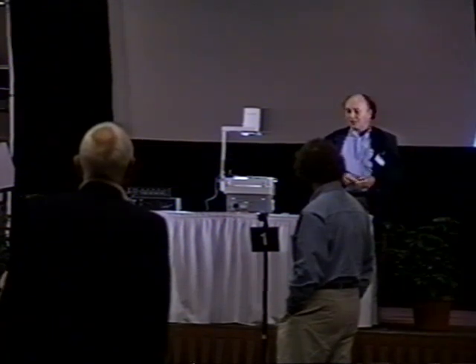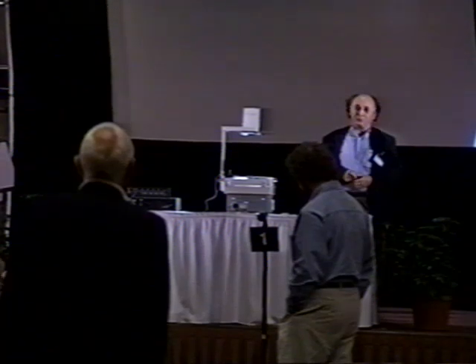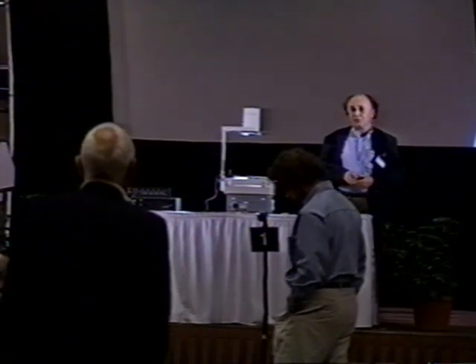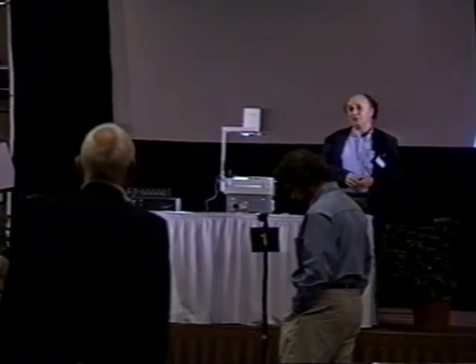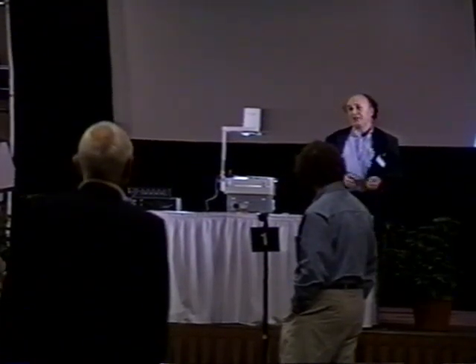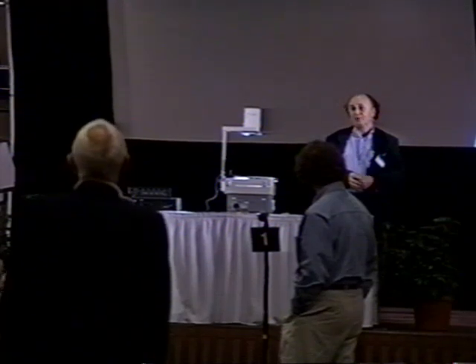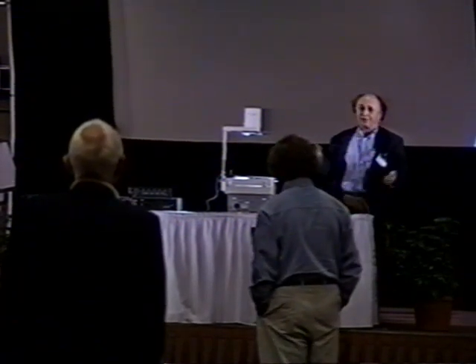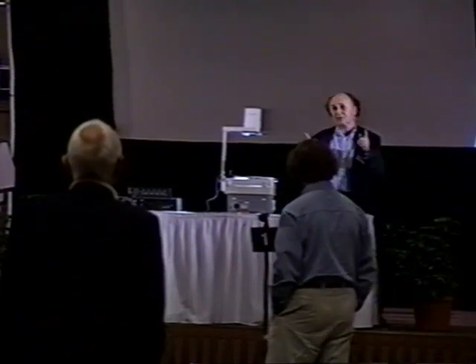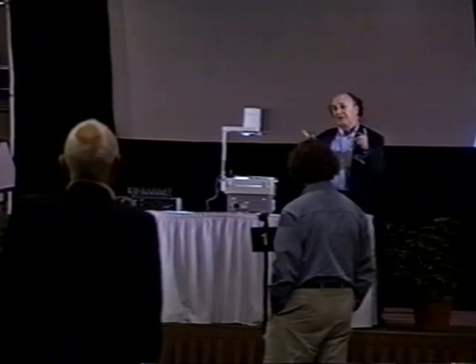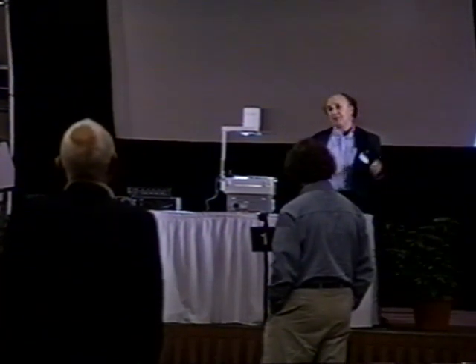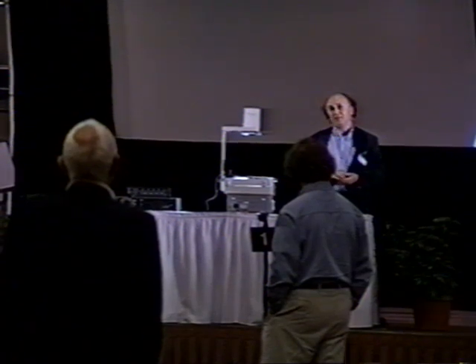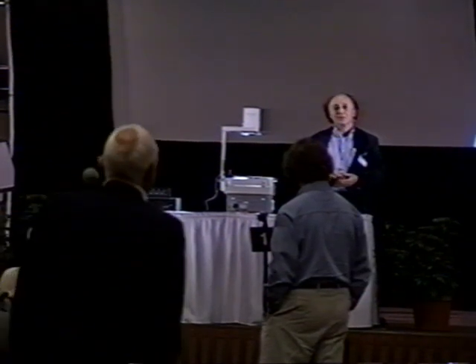And the yield you're observing, if you look at the pulse mode, we're talking about 2 milliwatts input, and we're getting 50 milliwatts. So we think we have about a factor of 25. But maybe it's more than that. We didn't try pulsing it less, because our time constant is 2 hours for the heat after death. So we could pulse maybe every hour, so that you're about at infinity. Thank you. Next question.